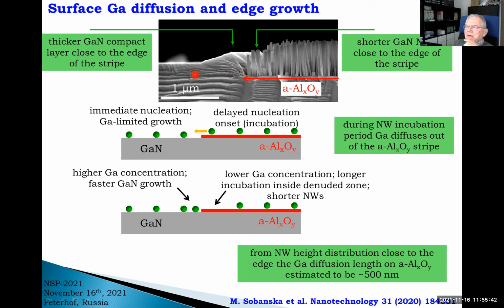The explanation is the following. Gallium nitride here nucleates immediately, because this is just homoepitaxy, while there is some time needed for the appearance of first gallium nitride nuclei at that part. During this incubation period, gallium atoms from this side diffuse and are captured by this growing gallium nitride, and because this growth is gallium limited, we have extra growth in that part. Simultaneously, the concentration of gallium atoms in this part on a stripe decreases, so incubation time increases here, and wires are short.